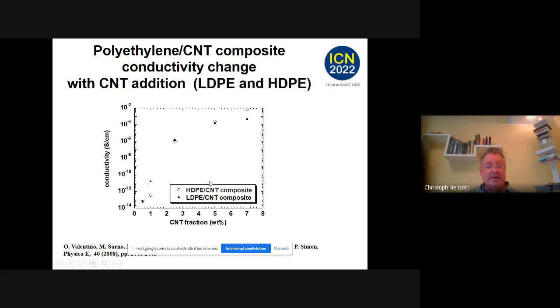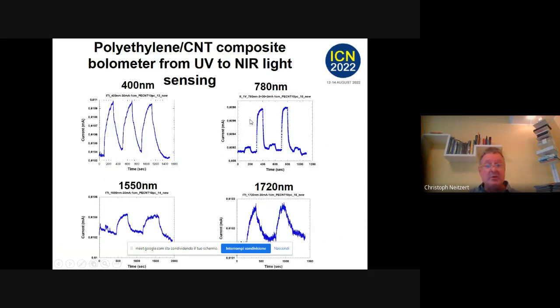And there we compared high density and low density composite long time ago. And you see you can again change the conductivity by about 12 orders of magnitude. Low density, high density, the threshold is not so different. It's very different in some other respects, but I will not go into details. And here I show just the bolometric response at 400 nanometers, 780 nanometers, 1550 and 1720 nanometers. So we go from the border of the visible UV to the infrared at 780. And you see here we have 3 milliampere, 30 milliampere. So we change the intensity.